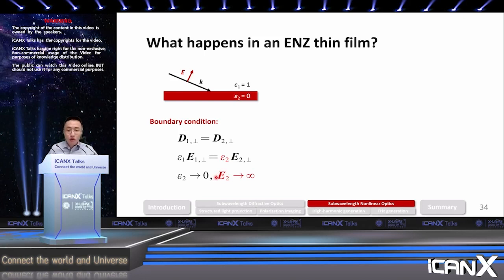In any realistic material, when the real part of its permittivity goes to zero, it is oftentimes also accompanied by some finite imaginary part of the permittivity. So depending on the magnitude of the imaginary part of the permittivity, you can still get a field enhancement maybe on the order of a few tens or a few hundreds.